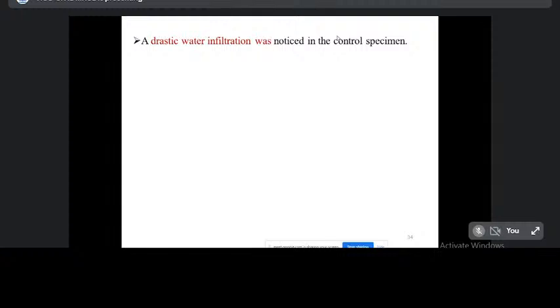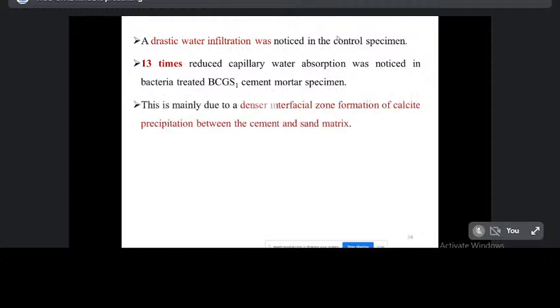From this observation, this is the conclusion we have derived. The first one is a drastic water infiltration was noticed in the control specimen. Then a 13 times reduced capillary water absorption was noticed in the bacteria-treated BCGS1 specimen. This is mainly due to the denser interfacial zone formation of calcite precipitation between the cement and sand matrix.